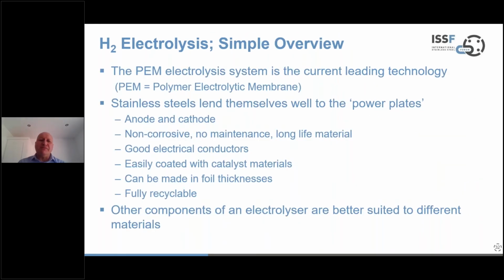Now, thinking about that, this polymer electrolyte membrane system is the leading technology for hydrogen production. It's not the only technology, and other technologies are present. But it's fair to say that when you look at the key elements of this, stainless steels do lend themselves well to the power plates, anode and cathode, primarily because they're non-corrosive. They don't require maintenance, so they're a very long life material. They are good electrical conductors. The coating with catalysts is relatively straightforward, and they can be made very thin, down to foil thicknesses. And as I've said, they're fully recyclable at end of life. When you look at other components of the electrolyzer, stainless could be considered, but it's not the most appropriate material or material family to consider.